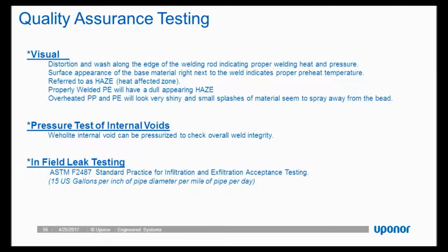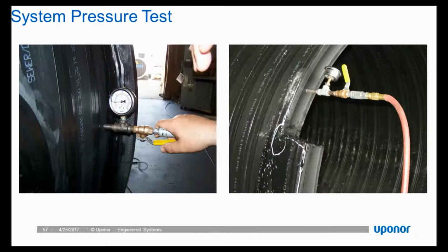Pressure test of internal voids is something that's unique to Weholite because we have a hollow annular space that is continuous through most structures. We're able to pressurize that internal void wherever there's a discontinuity, pipe penetration, top slab, or other fabricated element that might penetrate that void. We're able to pressurize that void and confirm that it is leak-free prior to it leaving the facility. And then the last line of defense for quality assurance testing would be, obviously most folks are aware of, infill and exfill testing, or some refer to as 24-hour drawdown testing, in accordance with ASTM 2487, which will fill the structure up and observe leakage rates.